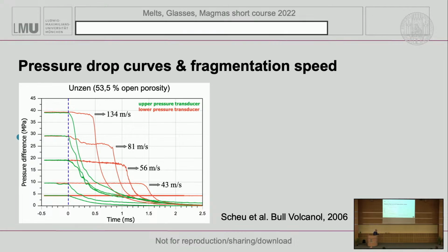What's taking so long? We're decompressing these things. Decompression is simply relieving the stress. Seismic propagation is all to do with the stress, right? The tensorial properties of the P waves and the S waves. Why is it taking 100 times as long to break the stuff as it takes for the acoustic information to go through the stuff? What we think is happening is that there is a crack propagation between bubbles, which has a characteristic length of crack, which has a characteristic time, and which is necessary for the macroscopic disintegration of the